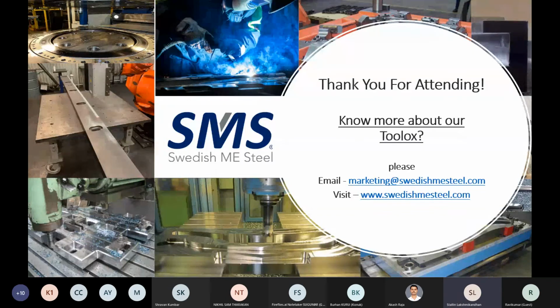If you're using P20 high hard, then you can directly try with Toolox 44. You can see the performance, whether you're getting any wear. Toolox 44 hardness is 45 HRC, sir. Is this good for 100% polishing surface? Is this material weldable? It is weldable, yeah. And the polishability you can achieve up to 5,000 mesh diamond polish.